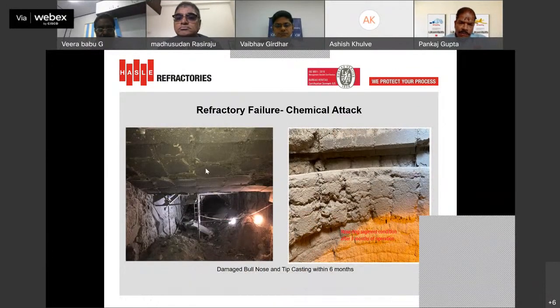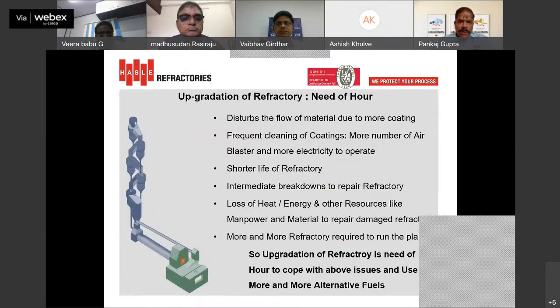In the same way, if your refractory is not capable enough to take care of these alkalis, sulfates, and chlorides, it will fail prematurely. You can see the picture of this bull nose, and also a picture from tip casting. So this is the need: when you are going to use alternative fuels, you have to upgrade the refractory, otherwise it will disturb the flow of material due to more coating formation.